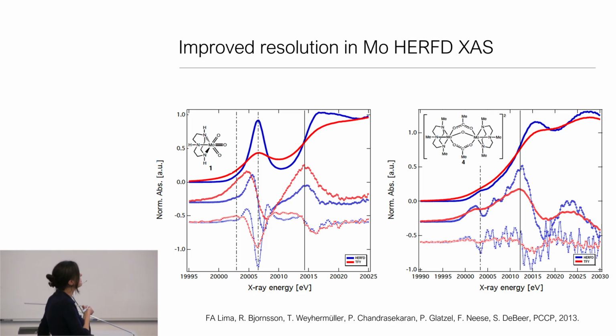And something like this molybdenum-3 that's completely featureless starts to have features in the HERFD detection, in the data, and in the derivatives. And the reason I'm bringing this up is because if we want to make quantitative comparisons to calculation, our data need to have features, right? And so it's not so satisfying to say it has an edge. Hopefully it has more than one feature. And so these can be helpful in cases where your data suffer from low resolution.